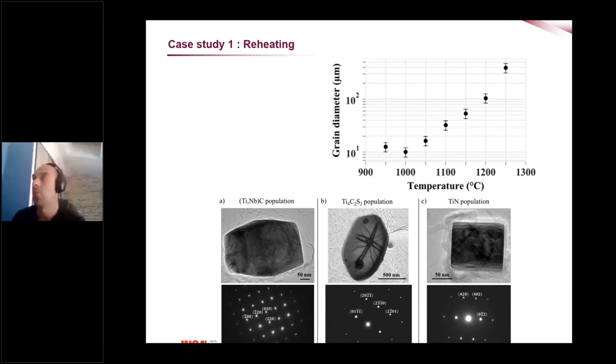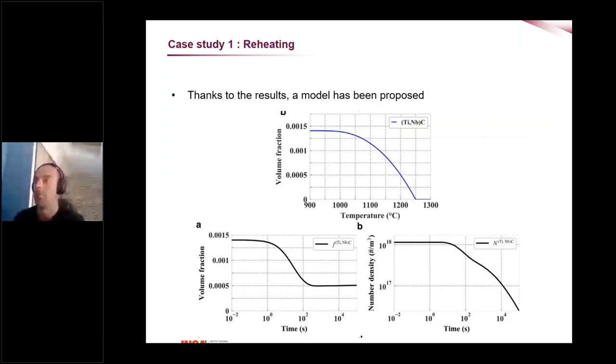As I said, we want not to get a very large diameter, but at the same time, we need to dissolve all the precipitates in order to get a lot of solute elements in solid solution to induce precipitation at the end of the process. So then we did some more experiments, and we did some calculations, and we proposed a model